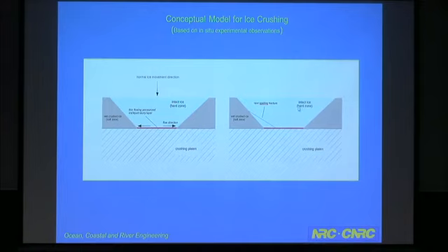So if you look at the image on the right, as this ice is moving towards this platen, stress builds up in the ice, and I've just shown one spalling crack that formed here. Very shortly after, and I mean on the scale of microseconds or milliseconds, that spall fractures. It becomes pulverized ice. It shatters, and then it joins the rest of the crushed ice at the sides.